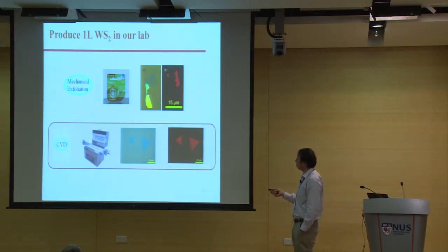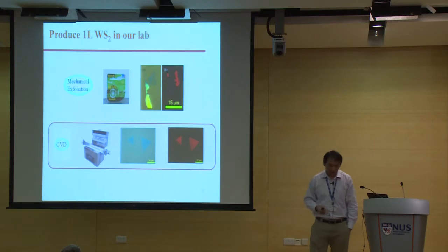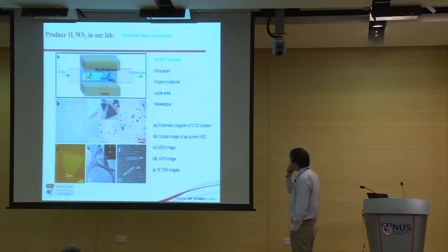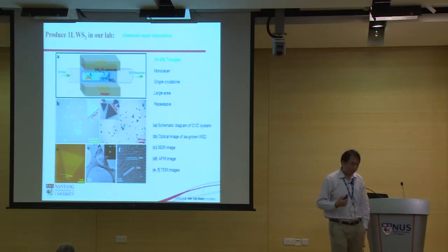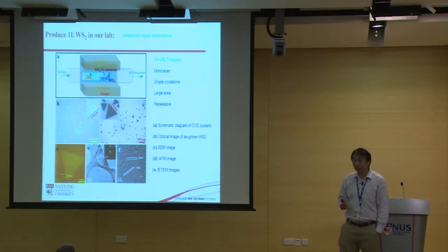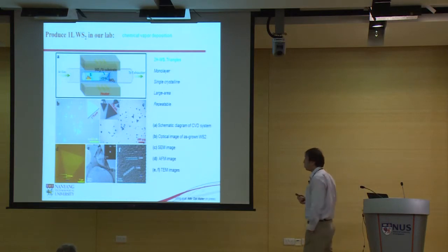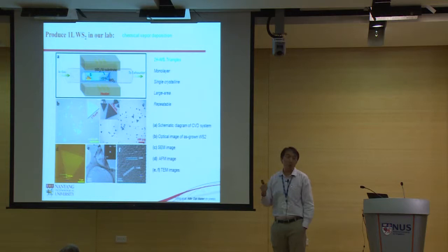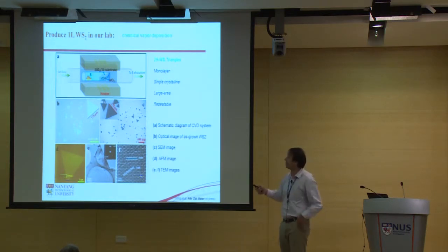the normal tube furnace, to produce high quality, large area monolayer tungsten disulfide. So the tube furnace is the same. The different thing here I learned from my previous experience when I did my postdoc growing metal oxide nanostructures. I introduced a one-end sealed smaller inner tube inside a big quartz tube of the tube furnace.